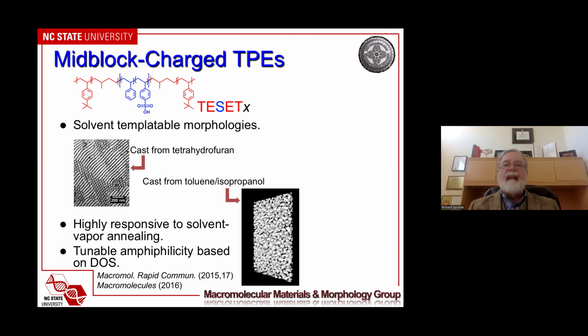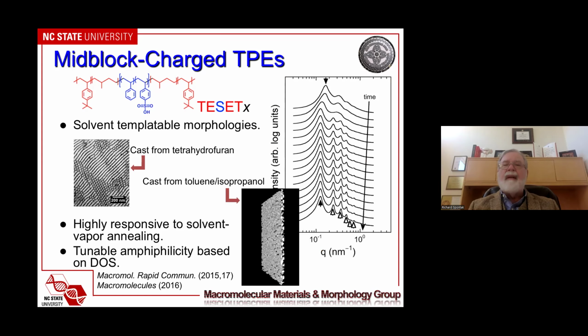And what that means is that we take a polymer film, it's a bulk film, so we're looking at from a half millimeter up to a couple of millimeters thick, and we subject that to the vapor of a solvent at room temperature. Now, just to put things in perspective, the glass transition temperature of these end blocks is about 130 degrees centigrade. And so room temperature is far below that. But what you see from these real-time small angle X-ray scattering profiles, we can start off with this morphology that you see here. That's this profile at time t equals 0. And then every one of those profiles is collected at 2 minutes.